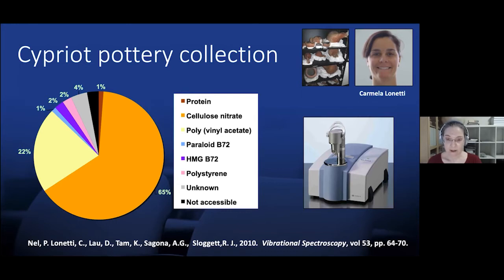Whilst doing this survey, we also documented the visual appearance of the adhesive repairs and would guess what the identity would be before it was revealed by the instrument. As our eyes became more focused based upon identifications made by the instrument, we started to make good educated guesses, but every now and again we would be surprised where the eye had been fooled. It was found that two thirds of this particular collection was repaired with cellulose nitrate, which is considered to only have a short lifespan in comparison to much better options.